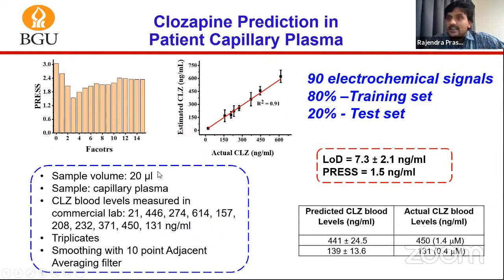And as I said, I used a 20 microliter volume sample of capillary plasma, and we have these labels in nanogram per milliliter. We use a 10-point adjacent averaging filter to smooth the data before loading it into the PLSR algorithm. Not only that, we also tested the model performance for the prediction of 450 nanogram per milliliter, and we received 441 nanogram per milliliter with this standard deviation, which is very close. And we also got 139 nanogram per milliliter for the prediction of 131 nanogram per milliliter. So that means our model and this multi-electrode sensor array platform is showing better sensing performance and allows us to predict clozapine level in a 20 microliter sample volume of the patient sample.